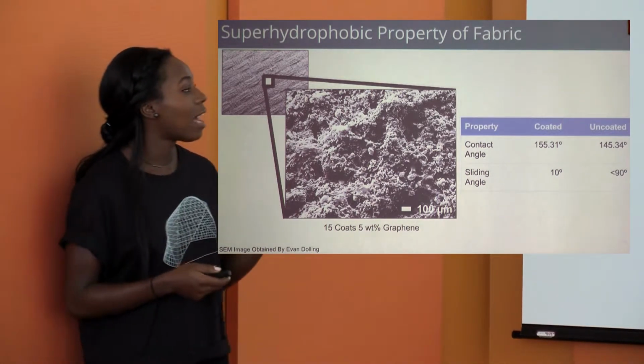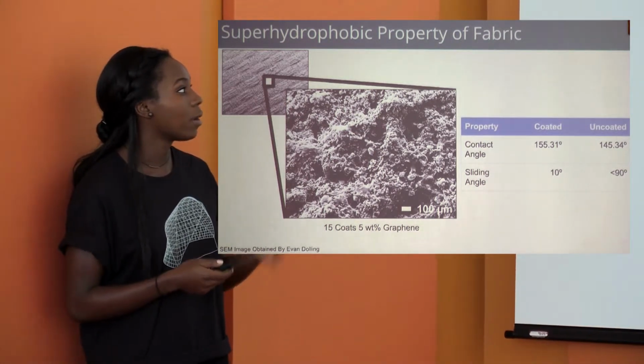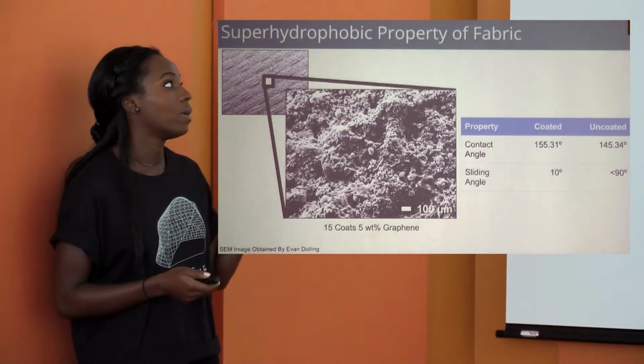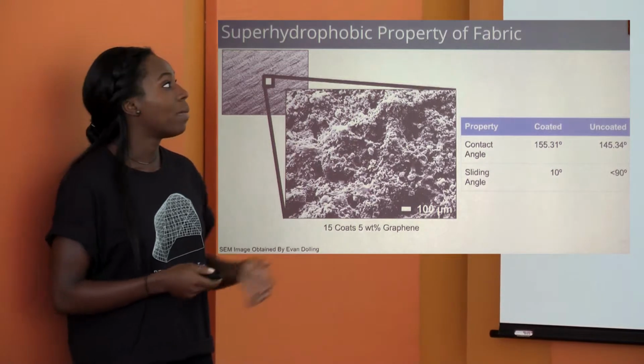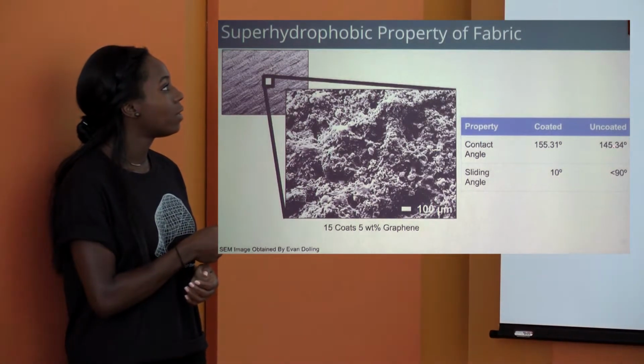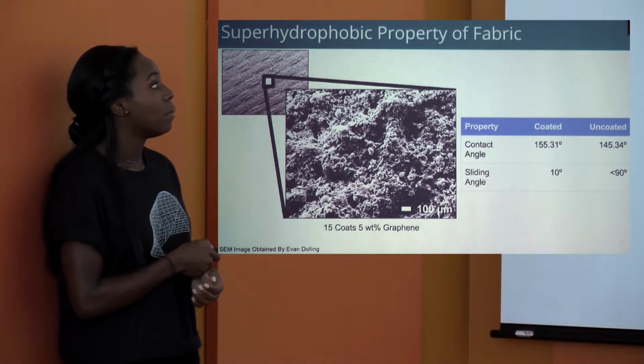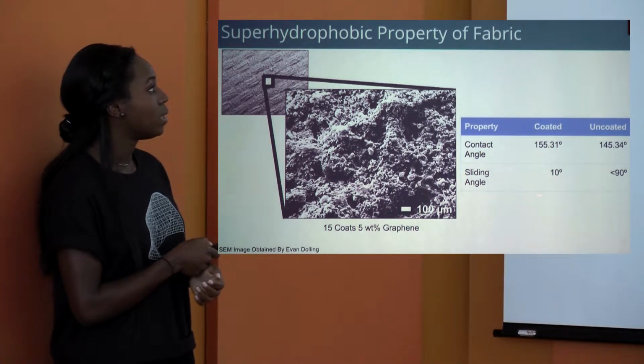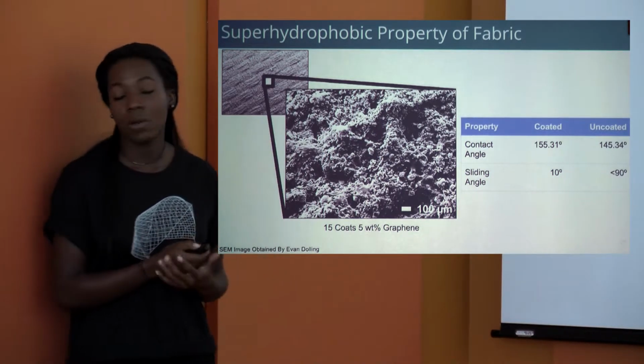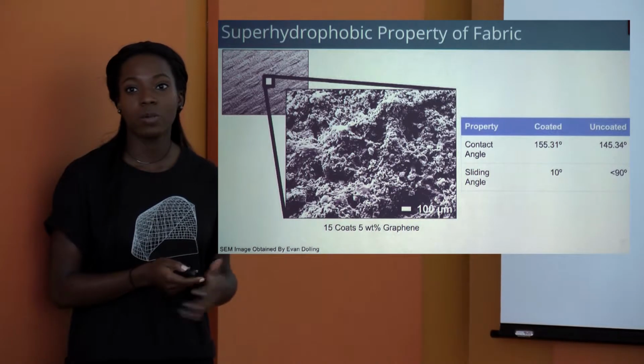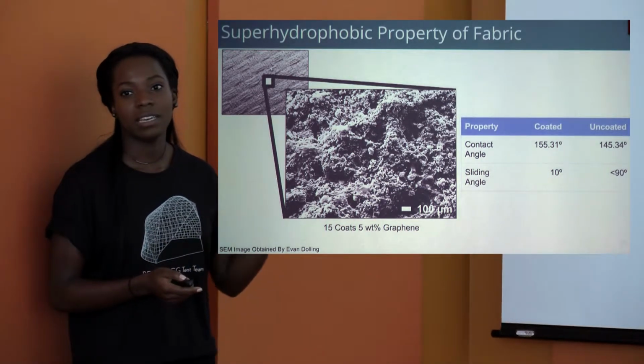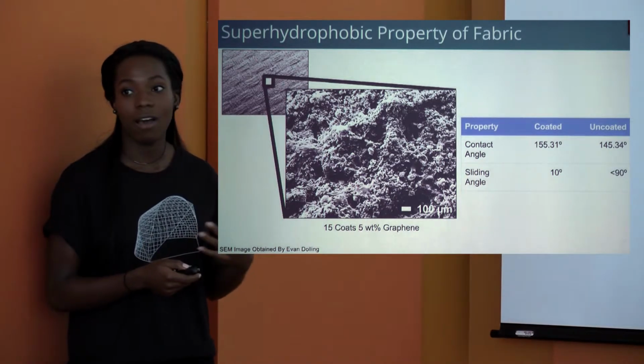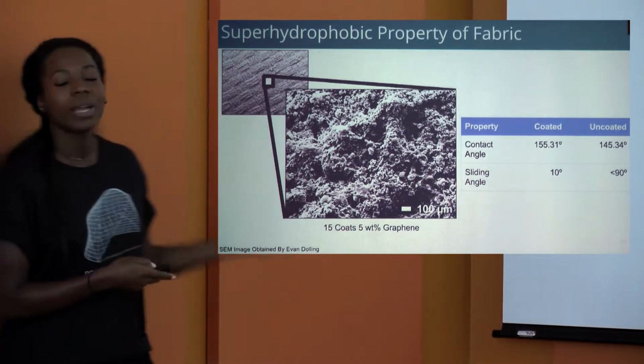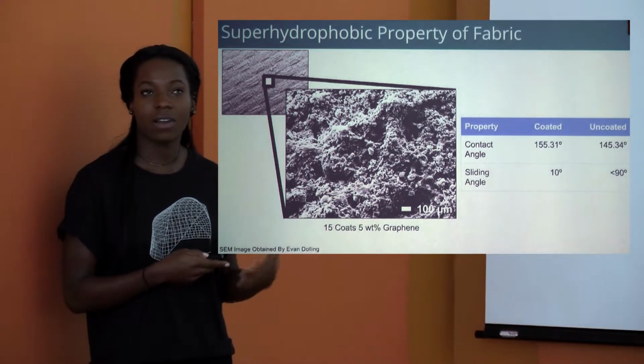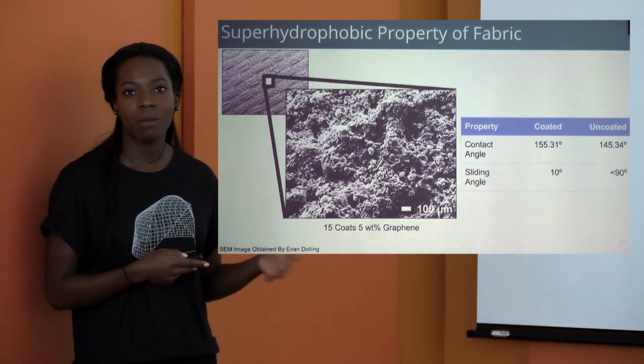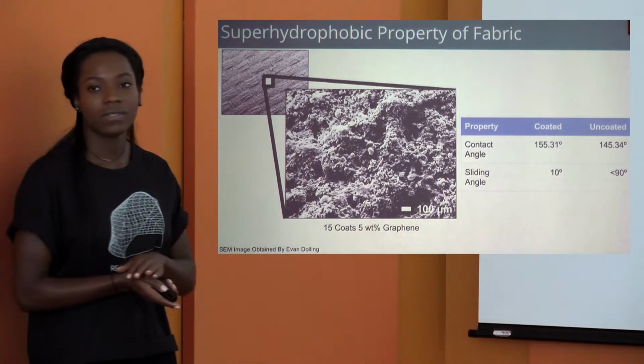And so we can see that with the contact angles of the coated and uncoated fabrics, our graphene particles did help us reach that superhydrophobic level by increasing the contact angle from 145 to 155. And also the sliding angle of the fabric with the coating was much lower than the uncoated fabric, which allows our tent to be even more slippery and for our water droplets to just roll right off. Although we were able to achieve this superhydrophobic characteristic of our coating on our tent, we did run into problems with adhesion of the coating to the actual surface of the fabric.